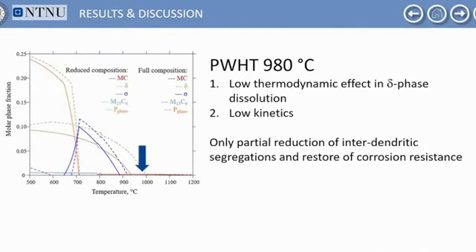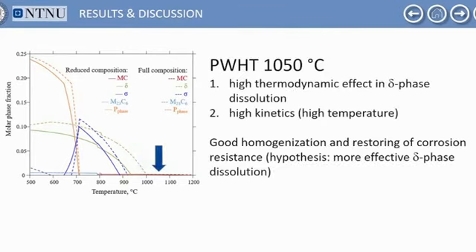Using a post-welded heat treatment, we can observe that we are able to redistribute such elements. We have a partial solubilization of delta phase, but at this temperature, 980 degrees, only a partial solubilization. On the other hand, with the highest temperature, we can reach the best result, because we postulate that we have a complete solubilization of secondary phases, so a complete restoring of corrosion resistance of this alloy. This is for both a kinetic reason and for a thermodynamic reason.